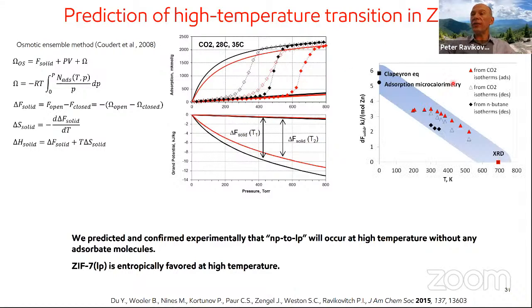And when you do that, you can see that this free energy difference actually has a temperature dependence, and at a certain temperature, particularly for ZIF-7, it is predicted that at a certain high temperature it is going to transition from a narrow pore to the large pore structure. And this is what has been observed indeed in the experiments.